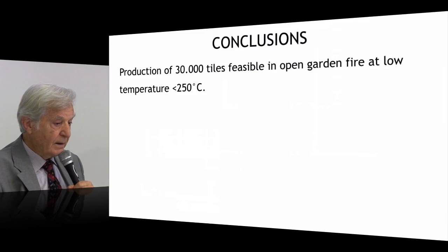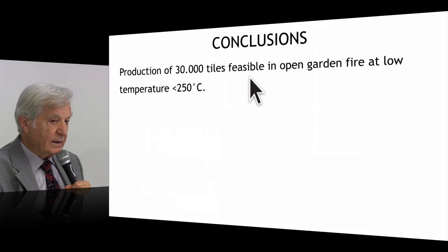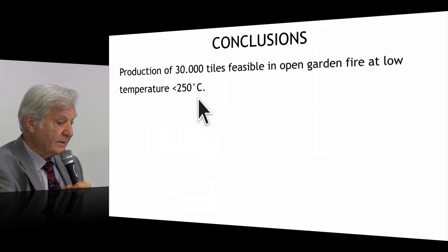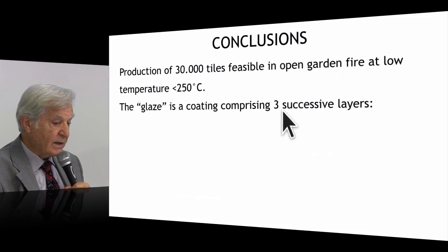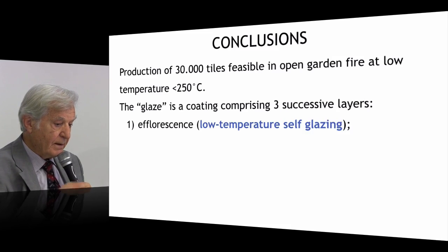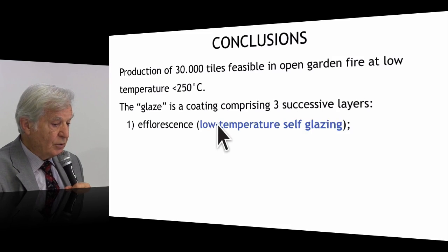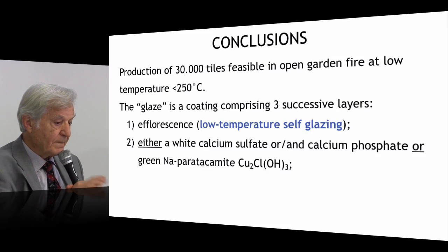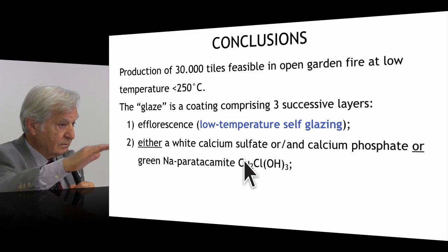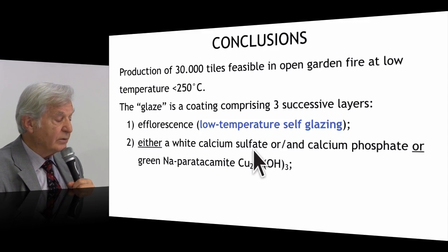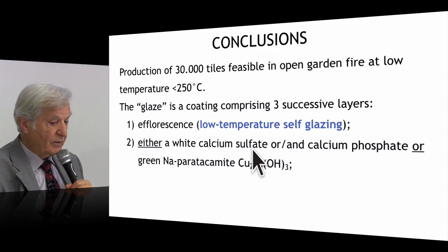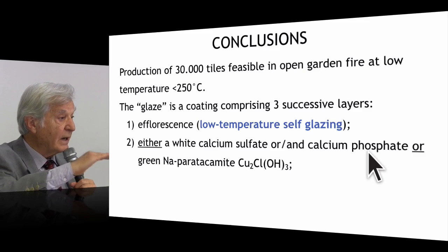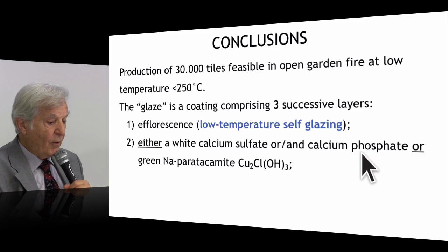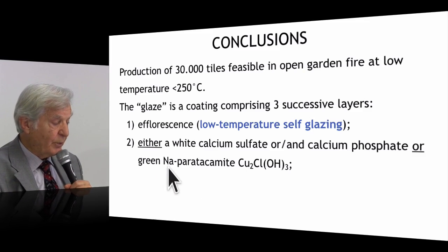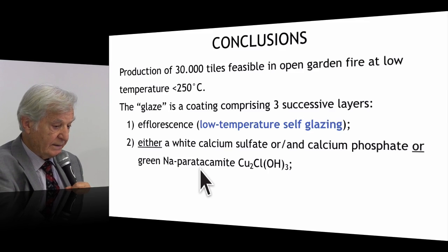So the conclusions. The production of 30,000 tiles is feasible in an open garden fire at low temperature, below 250 degrees C. The glaze is a coating comprising 3 successive layers. One, it is the efflorescence, low temperature self-glazing. Then we have a second layer, where either we found calcium sulfate on some tiles, or calcium phosphate on the layer under the glaze, or we found the green geopolymeric silicate layer with paratacamite.